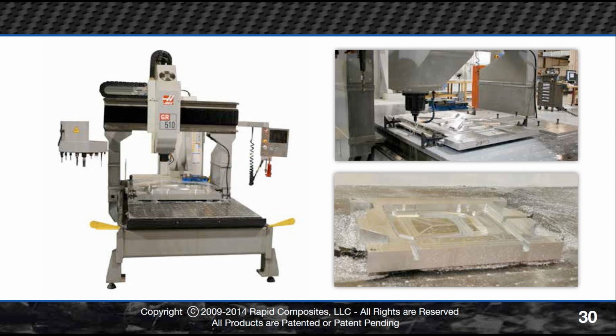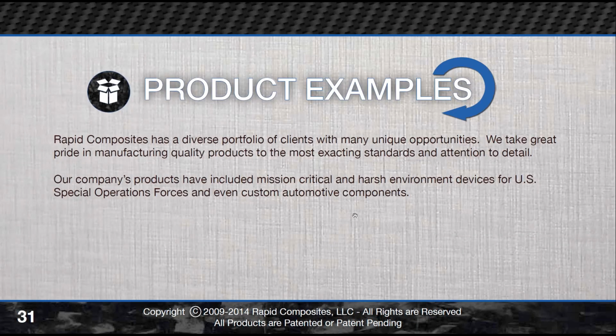When we have to go to higher temp materials, instead of running nylons or vinyl esters in the thermoset world, we go to something like PEEK or LCP, liquid crystal polymer, which are real high temp materials, we then have to go to steel molds. And the steel molds can typically, again assuming you have adequate draft, if you do P20 with S7 inserts, let's say, 50,000 shots to 250,000 shots is possible out of those tools. So the volume can go up significantly.